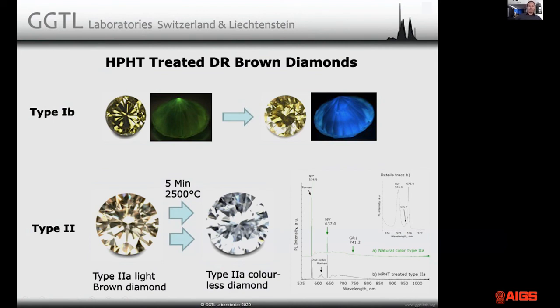Most famous in the market, type 2 diamonds. Type 2 diamonds, they require a somewhat higher annealing temperature. So usually you go probably somewhere between 2,300 and 2,500 degrees Celsius, just a short time. Any type 2 diamond will turn into its color without the brown. So if you have a type 2A diamond that was light brown, it'll turn colorless. If you have a type 2B diamond that contains some boron at least, it'll turn anywhere between gray and blue. If you have a pinkish brown type 2A diamond, it might turn pink first. And if you treat it again, it will go colorless. So this happens with type 2 diamonds.